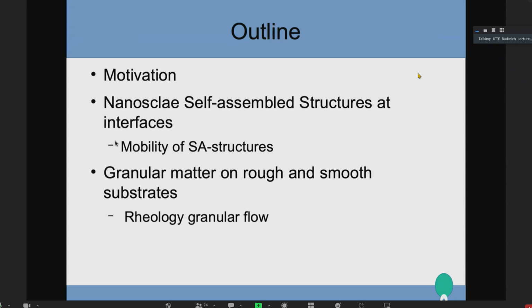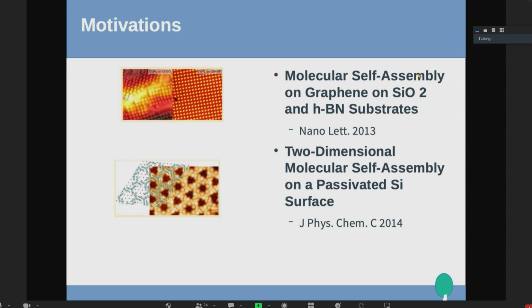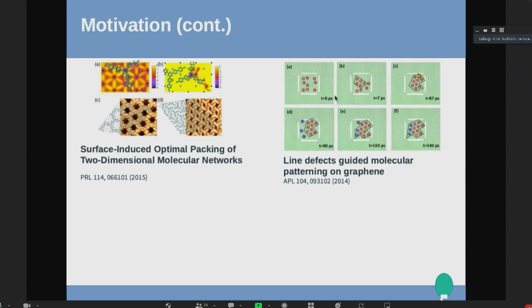I would take the opportunity to talk about two of our ongoing projects. One is a nanoscale self-assembled structure at interface that might be interesting for the audience here, and the second is the structure and rheology of ordered structure in granular material. It is not difficult to talk about the importance of self-assembled structure, and we had several outstanding talks on this kind of material. I show a few samples here. You see that for trapping a self-assembled structure on top of graphene and so on, it is difficult to have an island localized in a specific region.